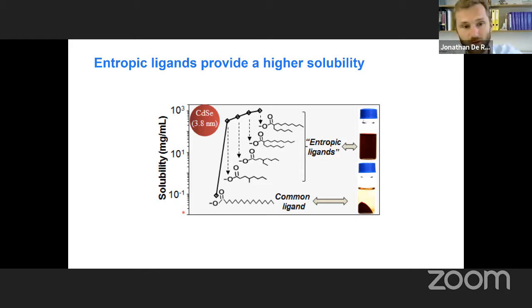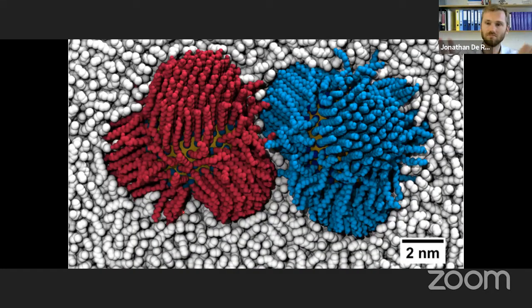And then another group that did fantastic work was the group of Todd Krauss. He looked with simulations where every atom was explicitly modeled, also the solvent. And he saw these kinds of pictures. So every atom of the solvent or every molecule is being modeled exactly. Here you see gold nanocrystals with, for example, hexadecane thiol ligands. And he saw exactly the same thing, that ligands crystallize on the nanocrystal surface in the precipitated state.